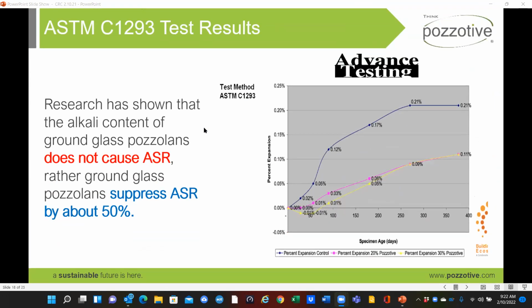to protect concrete. There's been noise in the marketplace. Well, you can't use glass in concrete because it creates something called alkali silica reaction, a gel that forms that caused bad effects in concrete. That's the case when you use it as an aggregate, and that's why we're out there constantly telling people you cannot use it as an aggregate in concrete. It has to be ground to a fine micron-sized particle where it creates this chemical reaction, and it actually reduces ASR when it's used in a mix.